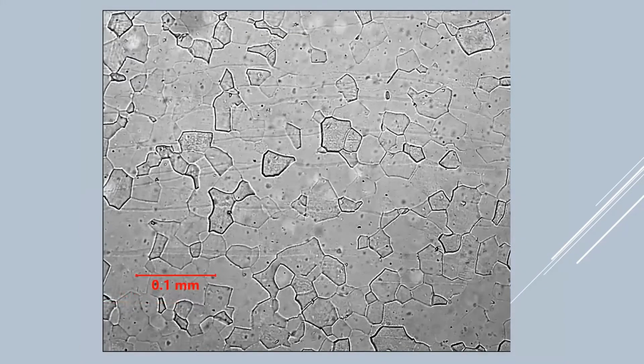I put this one in here only because it is another of the same. And first of all, we were getting that relief. Remember, we talked about that relief sometimes being caused by the cloth. The other reason is that you get that relief in surfaces that have almost no carbides in them, and I don't understand what actually is happening there. So getting relief on a decarburized surface is quite common. Those wavy lines that you see on there are strain lines, or sometimes called strain markings. What they mean is that that pressure vessel was cold rolled and was never heat treated. And considering the age of that vessel, that's probably pretty common too.